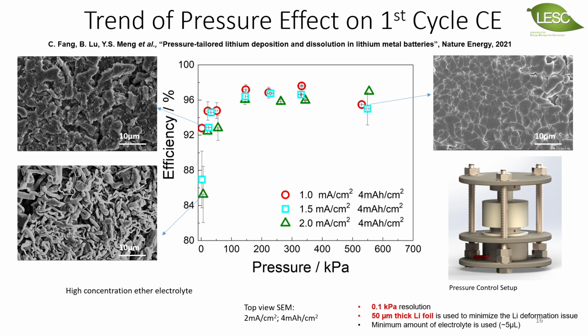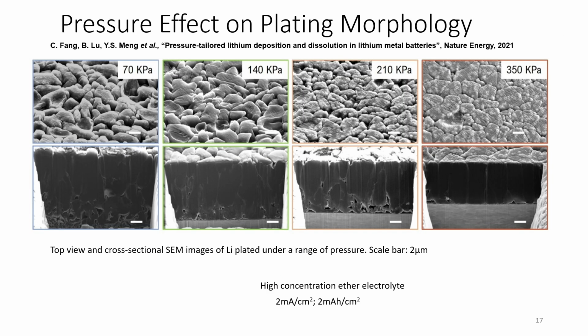So we still don't have the full understanding about the lithium nucleation in the organic solvents. All we observe is that it's very, very porous. So if I show you the cross-section image, it's even more astonishing because these are exactly the same condition, with the only exception being the stack pressure is 350 kilopascal, about 3 atmospheres. These scale bars are the same.